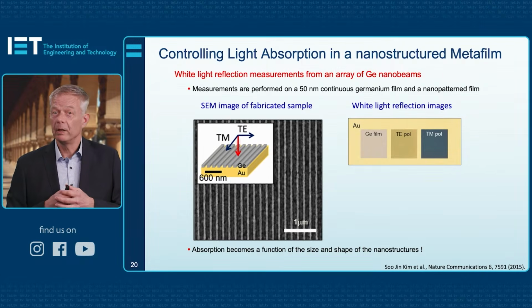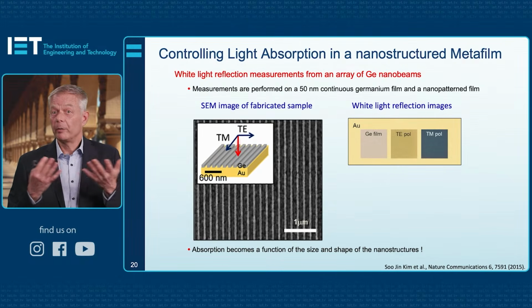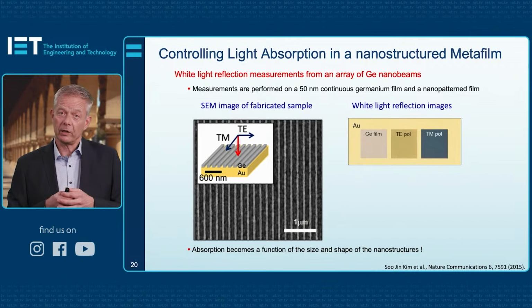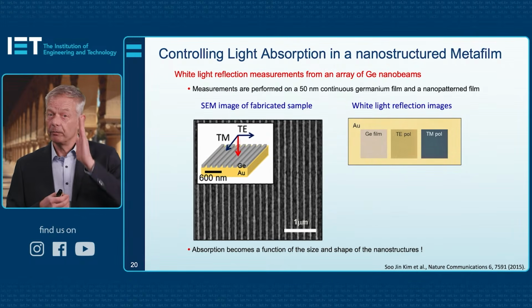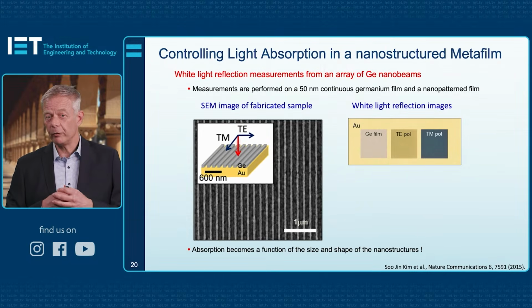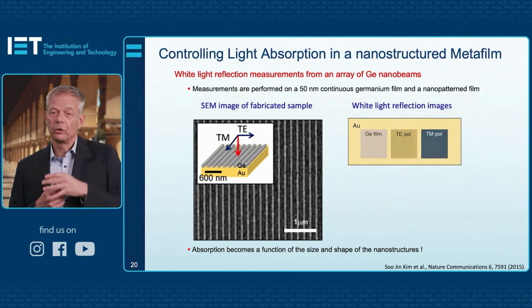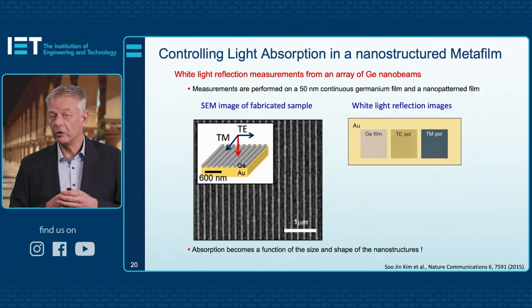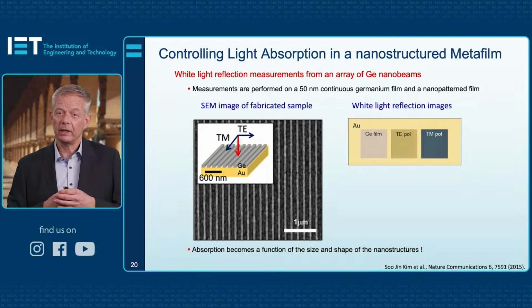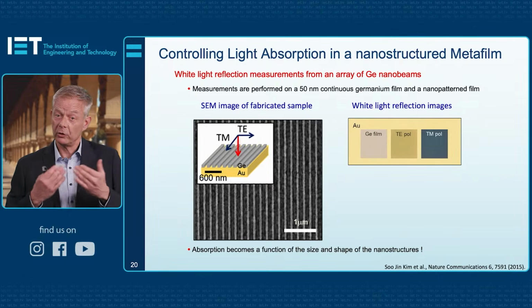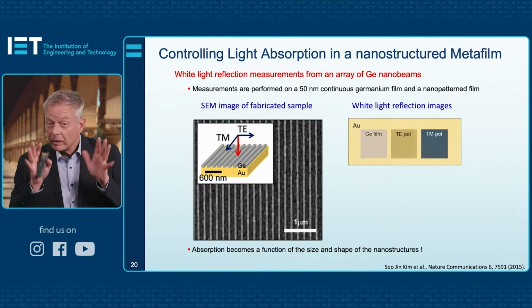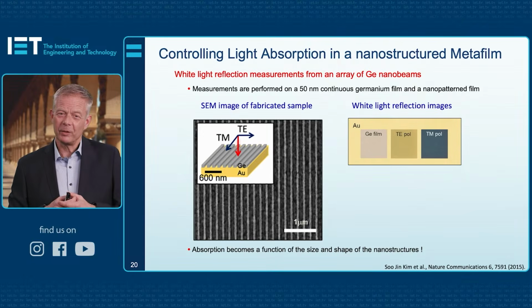On the right side, you see white light reflection images, both of the continuous film, in this case of germanium, which looks a little grayish, and that's because germanium absorbs broadly across the visible spectrum. But if you have the electric field along the wires or orthogonal, you see very different behavior. When the electric field is orthogonal, it looks a little goldish, which is the mirror-like substrate that we have underneath, that you can see through the bars of germanium.